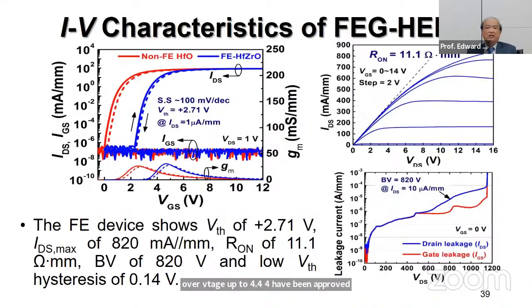Next. The initiation process is 12 volts for 1 millisecond, and then a large VTH shift up to 4.4 volts has been observed. And this is the IV characteristic of the ferroelectric gate materials. It shows that in this case the VTH is higher than 2.7 volts, which is more than what we require, 2.5 volts, and the RON is 11.1 ohm millimeter, and the breakdown voltage is around 820 volts, and the threshold hysteresis is very small, only 0.14 volt. That means the interface of the layers has very few electrons trapped in the interface.